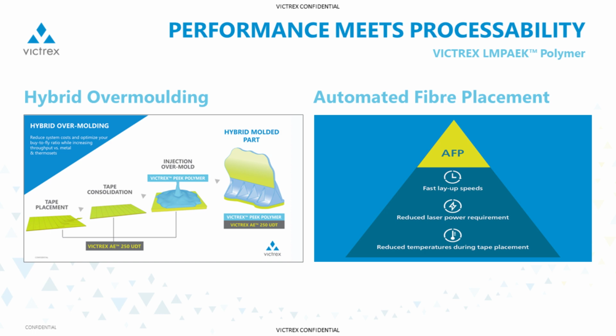And then finally, there's a lot of information, I think, in the public domain about the use of the low melt PAEK, or AE250, in UD tape format, but being processed through automated fiber placement. And we think a lot of this benefit comes from being able to move along the viscosity curve and get a better flow of the polymer while doing these rapid laydowns, and then ultimately yielding higher quality laminates from that process.